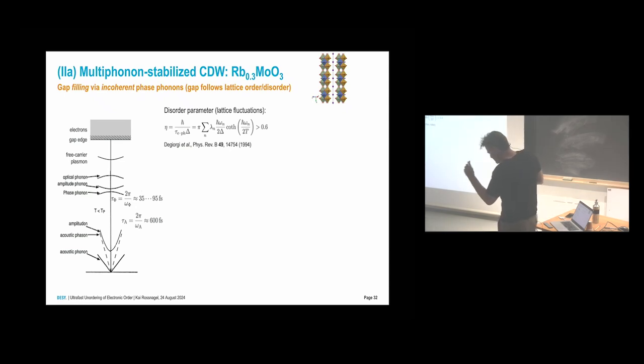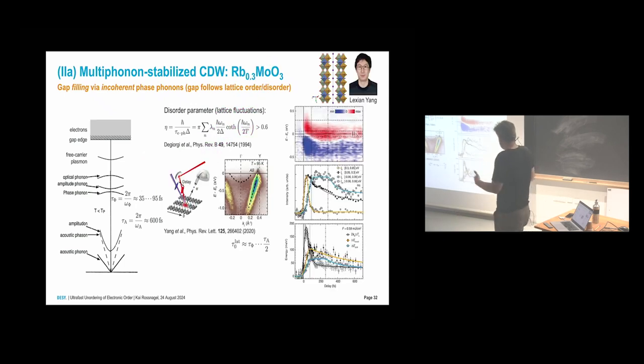You now introduce incoherence in the system, and the measure is that you relate the energy scale for electron-phonon scattering to the gap size. If you have strong electron-phonon scattering, you can imagine that you will smear the gap and fill in spectral weight in the gap. And this disorder parameter is very large for these types of systems. In our time-resolved ARPES study, by Lexian Yang in the group of Michael Bauer and myself, we have looked at the gap.